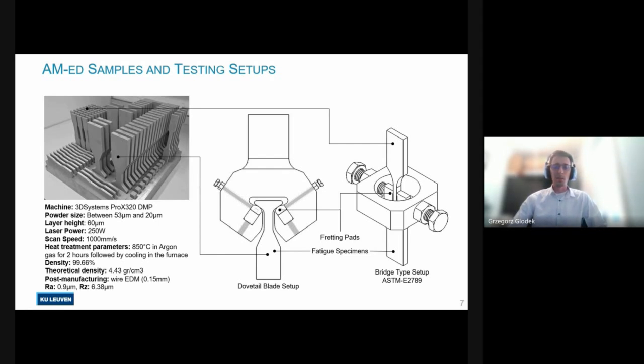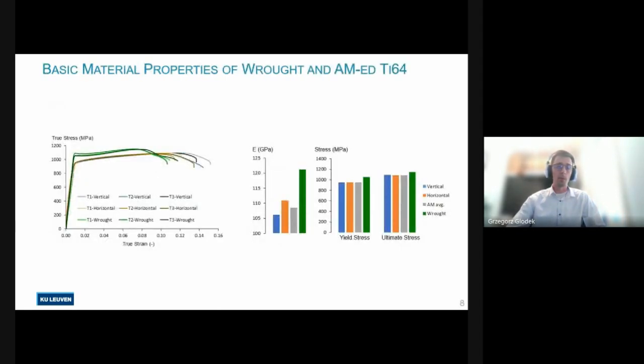After the printing process, the parts underwent standard heat treatment at 850 degrees in argon atmosphere for 2 hours, and were later cut to the final dimensions using wire EDM, which resulted in a final surface roughness of Ra value 0.9 micrometers. So in this presentation, I will mainly focus on the results of the dovetail blade setup shown here in the middle. But first, just a few more words about the material properties.